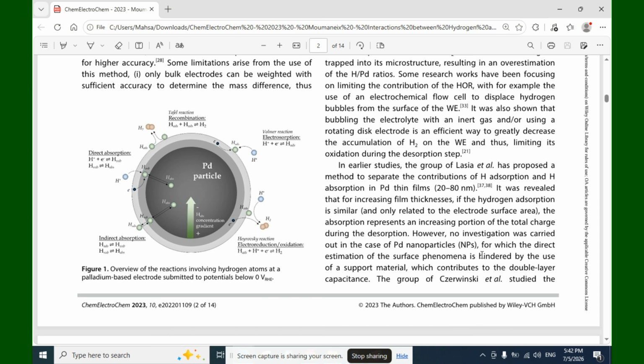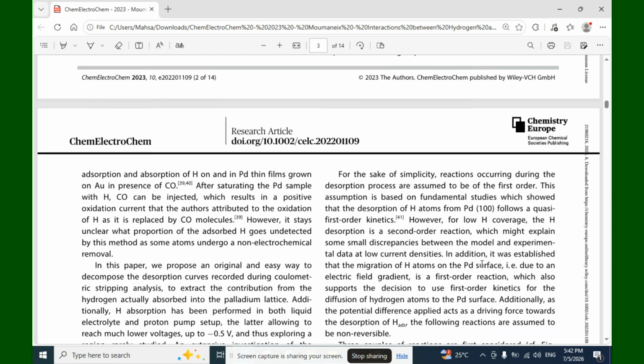The group of Czerwinski and his colleagues studied the adsorption and absorption of hydrogen on and in the palladium thin film grown on gold and silver in the presence of carbon monoxide. After saturating the palladium sample with hydrogen, carbon monoxide is injected, which results in a positive oxidation current. The authors attributed this to the oxidation of hydrogen as it is replaced by the carbon monoxide molecules.